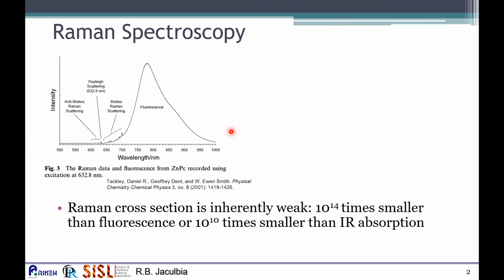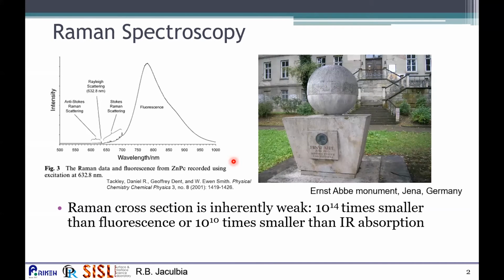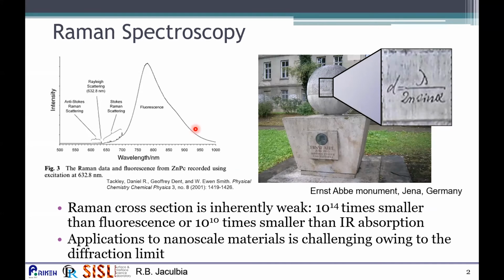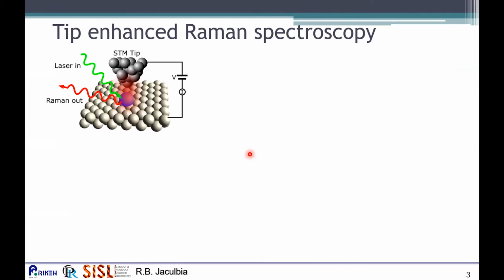Moreover, the application of Raman spectroscopy to nanoscale materials is quite challenging owing to the diffraction limit, which limits the spatial resolution of Raman microscopy to about half the wavelength of the incident light. So in order to solve these two problems, one technique that can be applied is so-called tip-enhanced Raman spectroscopy, wherein we use the tip of a scanning probe microscope such as STM or AFM in order to enhance the Raman signals and therefore improve the spatial resolution.